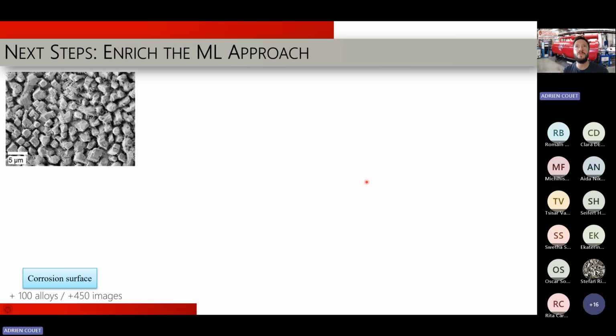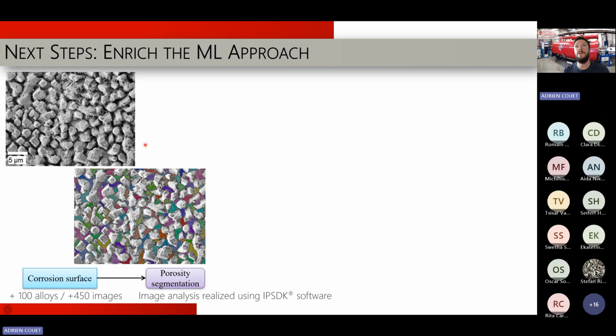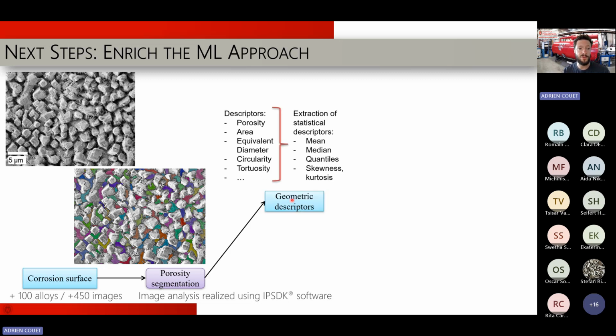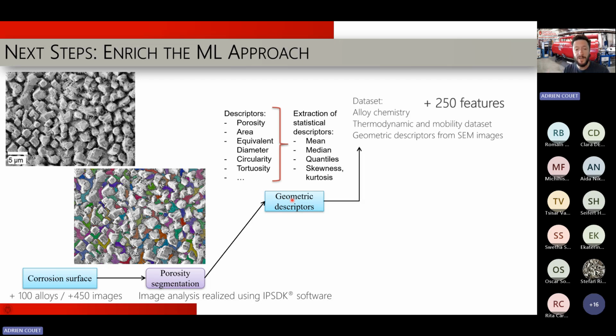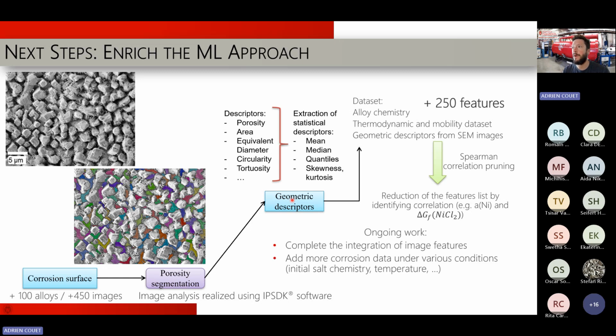And the last slide here is we're also looking at doing machine learning on the facets, or on the morphology of the surface. So, for instance, we can use computer vision aided software, that is machine learning based, to extract the porosity on these images. And that helps us to get more descriptors, more features, right? So we have much more features than just the 75 I talked to you about. We now have more than 250 features. So we can really enrich our machine learning random forest regressor. And we also then want to use Spearman correlation pruning, and at the end arrive at, maybe using the morphology of the images afterwards to better inform if it's related to the corrosion rate, as I mentioned earlier.